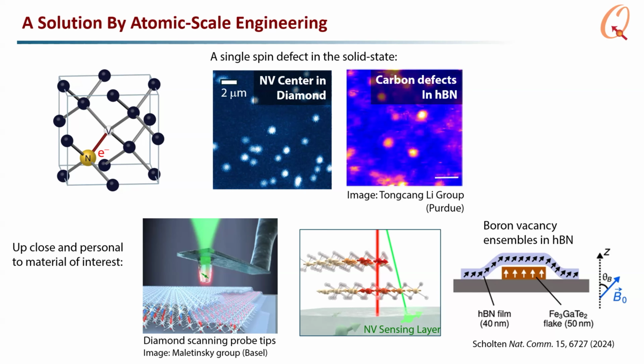So for example, you can fabricate diamond scanning probe tips. This is from the group of Patrick Maletinsky in Basel, or you can just put materials on top of diamond where you have these sensors right underneath within nanoscale proximity. And even in these van der Waals heterostructures, if you have defects in hBN as already part of your heterostructure, they can provide an embedded reporter of the material properties. You can actually buy these tips commercially from these companies in Switzerland right now. We buy our tips from QZabre.